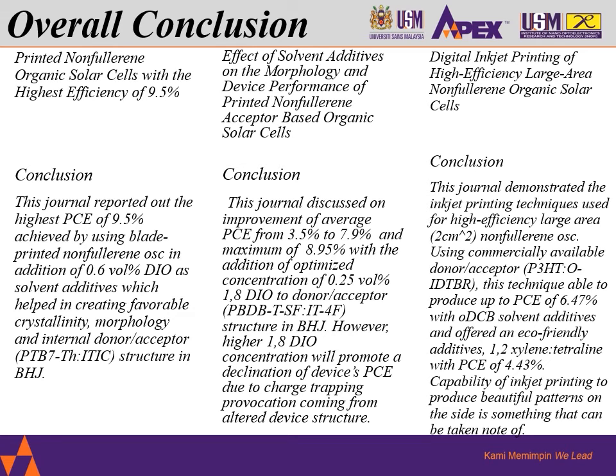The second journal concludes that the improvement of average PCE was achieved from 3.5% to 7.9%, and a maximum of 8.95%, with the addition of an optimized concentration of 1,8-DIO, which is 0.25 volume percentage, to the donor acceptor structure in the bulk heterojunction. However, a higher 1,8-DIO concentration will actually promote a decline of the device's PCE due to charge trapping coming from the altered device structure.